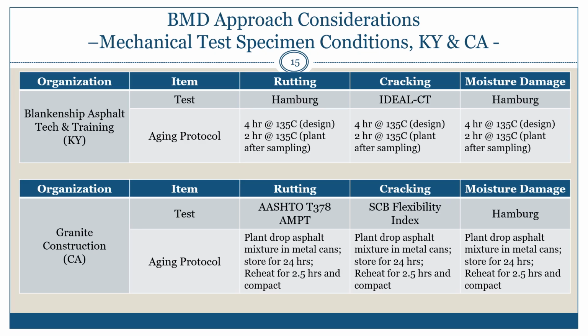The work being done out in California and provided to us from the boys over at Granite, you can see here that they've got quite different methods with respect to how to sample the material. Plant drops in metal cans, storing it for 24 hours, and then reheating it for 2.5 and compacting. Very specific methodologies that they feel works well out in Caltrans. The same exact thing for the flexibility index and the Hamburg. So important to understand when working with a state agency that their criteria may be different, but not just the criteria, but also the way that we handle the materials. And that's all going to be reflected in the final outcomes and performance of these different performance tests.